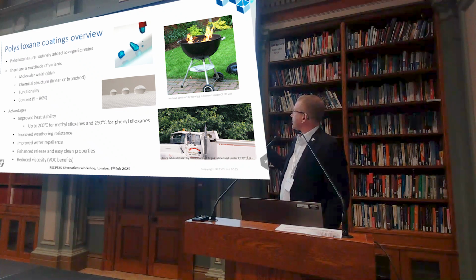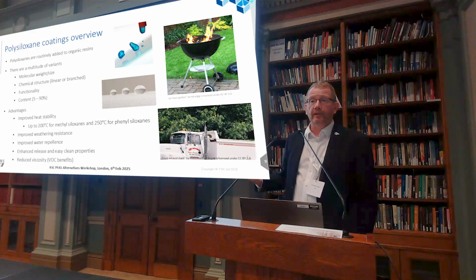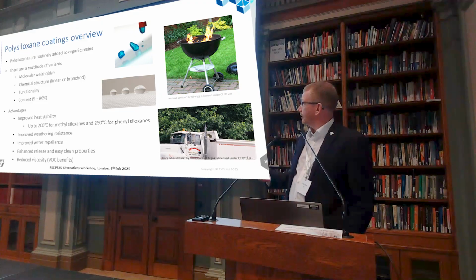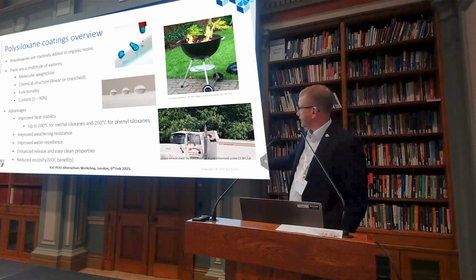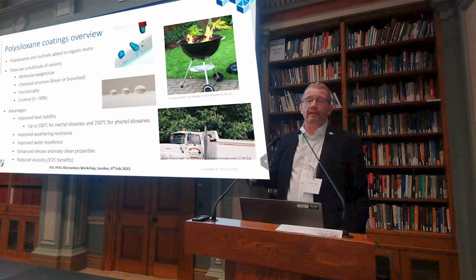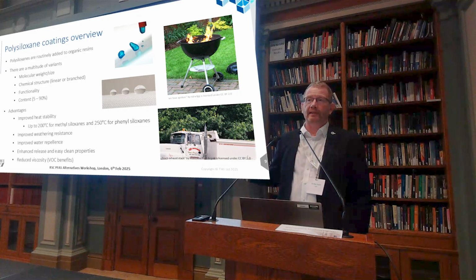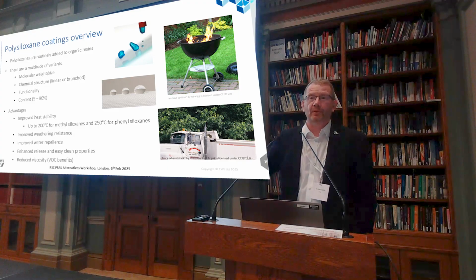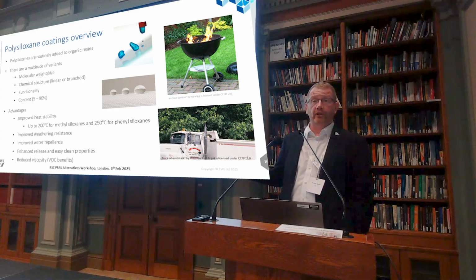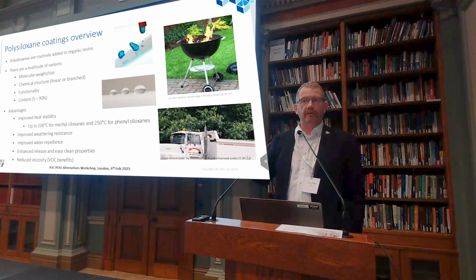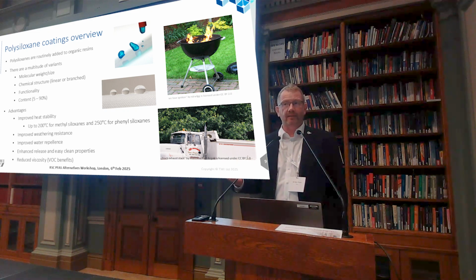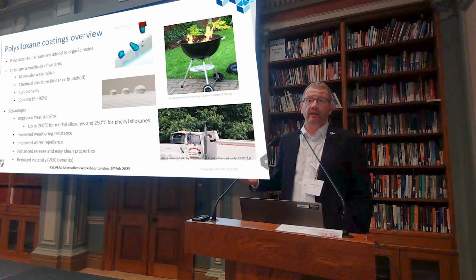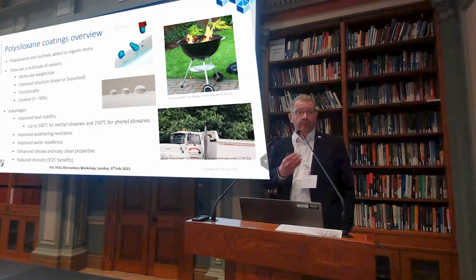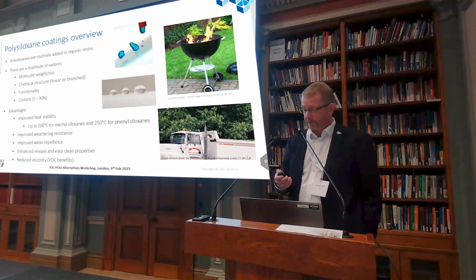Well, you can have siloxane-based coatings that have very high temperature capability. They can be very hydrophobic, and they can also provide barrier properties. The example at the bottom here is a stainless steel exhaust stack that is protected with a polysiloxane barrier coating to make sure that the stainless steel doesn't change colour when it gets to a high temperature. High temperature for stainless steel to change is 400 degrees C. Polysiloxanes, in their broadest sense, have an awful lot of capability, and I think it is an opportunity waiting for people to start to exploit and explore. And I know some of the manufacturers in the room are already starting to look at some of these things.